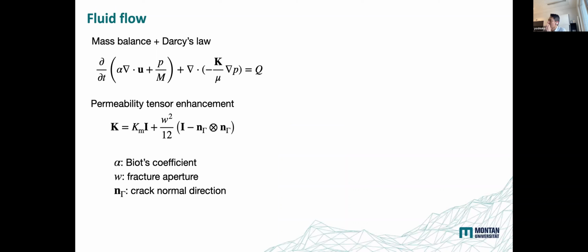No, it's not coupled. The phase variable tells us whether the material is broken or not broken. Even if the material is fully broken, meaning that the phase variable is completely zero, there could be a case where the fracture is completely closed, and then the fracture aperture can be zero. So the fracture aperture is coming from the deformation, but the existence of the fracture is coming from the phase field variable. The phase field variable gives us an indicator, and the actual value of the fracture aperture has to come from the deformation or the displacement.